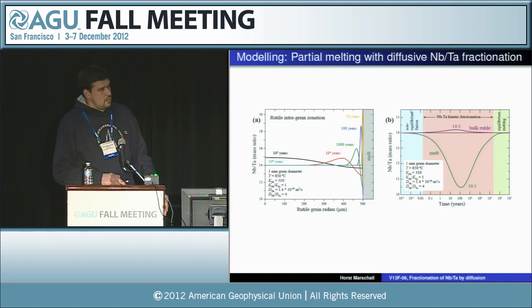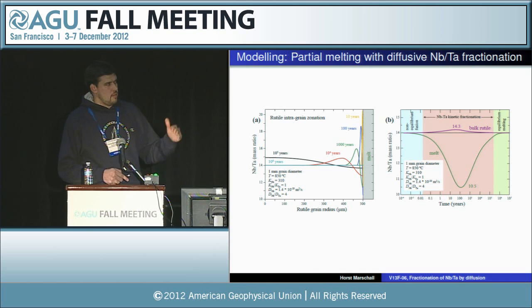So you can look at this in a different way. This is time versus niobium-tantalum ratio, starting at bulk silicate earth value, 14 on the left side here. And for the first few months or so, there's no equilibration. Both niobium and tantalum are too slow to do anything. So I call this the non-equilibrium fusion scenario. Then in the red area, you have a strong kinetic fractionation of niobium and tantalum.